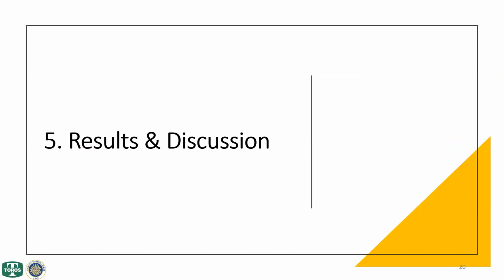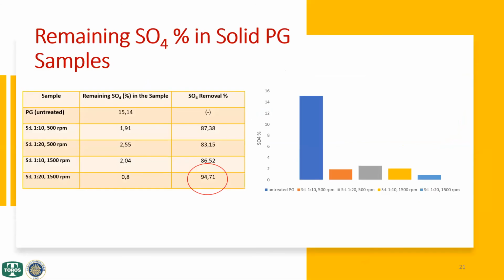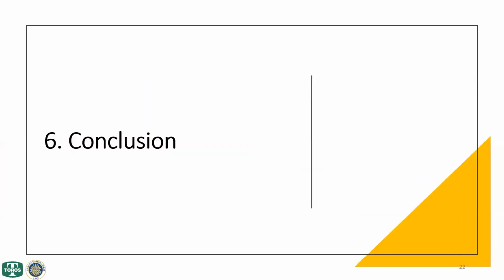So I will give the results. From the first row, we can see that untreated PG has a sulfate percentage of around 15. And the highest removal efficiency is observed at the dilute solid liquid ratio, which was 1:20, and fast mixing rate. So we can see that an increase in the mixing rate allows more interparticle contacts in the experimental media, resulting in an increase in sulfate removal rate.